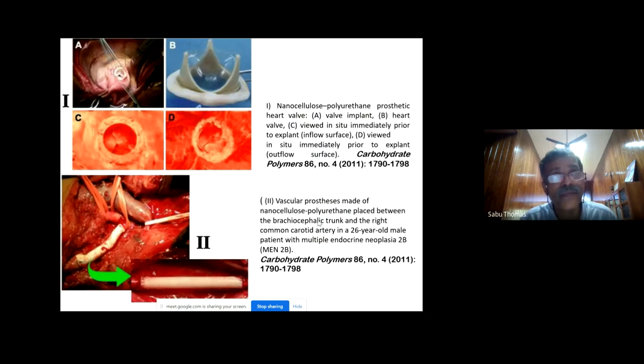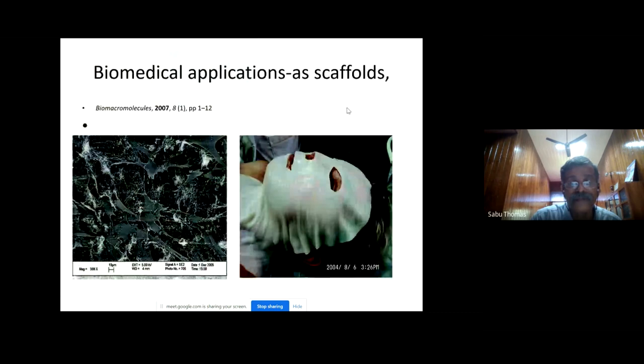And eventually, dear colleagues, what we did, my Brazilian collaborator and I, we made a nanocellulose polyurethane prosthetic heart valve in a Brazilian hospital. And we published a large number of papers, and my collaborator has a very interesting patent. We can also utilize nanocellulose gel as a scaffold for burns. You can see a gentleman suffering from a high degree of burns on his face. And his face is completely covered with nanocellulose gel. Nanocellulose gel is extremely porous. Therefore, the tissue regeneration is quite rapid.